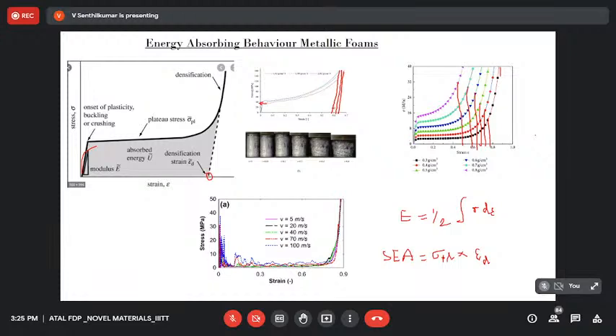As you increase the density, you will get slightly higher energy absorption for a higher density material. But this behavior keeps reducing, and you cannot use this material for energy absorption after a certain point. If it is less than 0.5, it is not of use. The strain has to give at least 50%; 0.5 will be the true strain. Beyond that, it will not be very effective. So it changes from material to material.